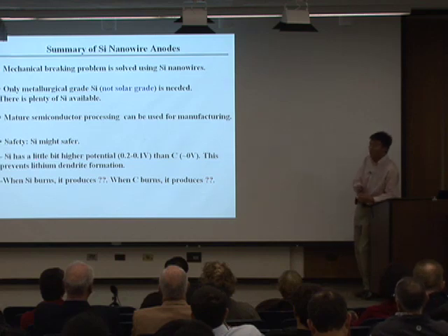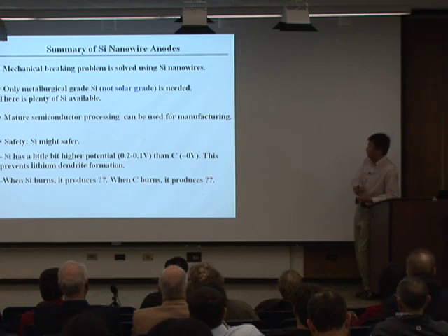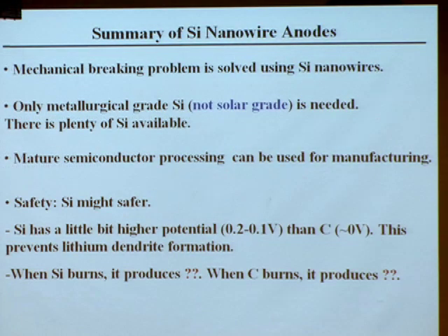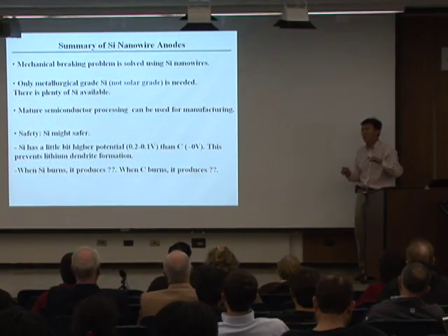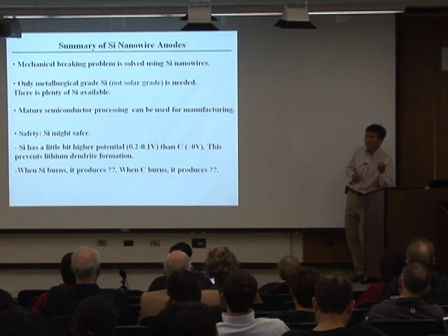So silicon, when you charge lithium into silicon, the potential is higher than lithium metal by about 100 or 200 millivolts. Well, if you use carbon, which is the existing technology, that's really close to 0 volts compared with lithium metal. So carbon has this well-known problem: lithium dendrite formation if you charge your batteries. When lithium dendrite is formed, that causes shorting, which causes explosion of the batteries later. Particularly in cold weather, lithium dendrite can be formed even more easily if you overcharge it. Now you have this potential slightly higher than lithium metal. That allows you, when you use silicon, to prevent this lithium dendrite formation problem.